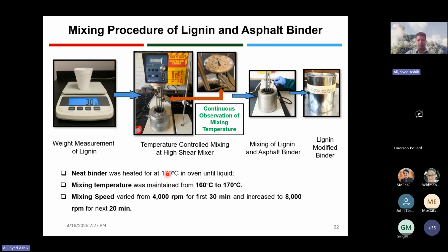During the shear mixing, you can see this is the high shear mixer that we have used for this purpose. The mixing speed we maintained, initially we started with 4,000 RPM for the first 30 minutes, and then we increased that speed to 8,000 RPM for the next 20 minutes to make sure there is a continuous and uniform mixing of lignin within the asphalt binder. During the mixing procedure, we try to maintain the temperature between 160 and 170 degrees Celsius. As you can see, we were continuously monitoring the temperature so that it doesn't go below or above that range. Through this process, we were able to produce the 5% lignin and 10% lignin, the two we wanted. And we also used a similar procedure when we added the SBS, styrene butadiene styrene.